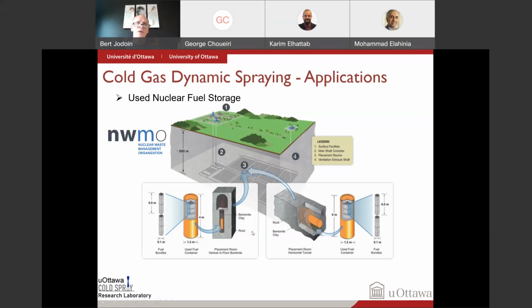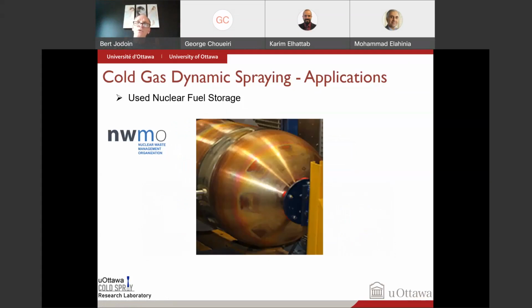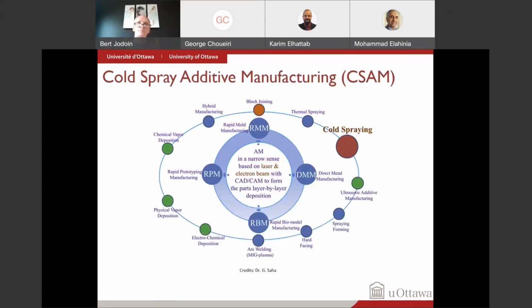So what we do is we take the fuel bundles, put them in this container, and then we need to cap the container. So we screw the container and we weld it. The weld needs also to be protected by copper, so that's what we do using cold spray. So you see the cap here of the container and the weld here, and after that, we do cold spray this with copper and we polish it before it gets put underground. So the video you saw a bit earlier was when we were trying out all the spray parameters to be able to coat the weld region.